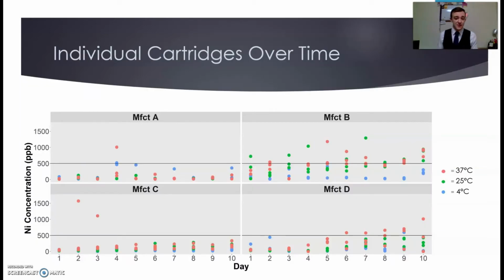This plot here shows individual cartridge nickel concentration for each of the 10 days for all 4 of the manufacturers we tested. And it really starts to show a lot of the relationships that we were able to extrapolate from this data. First off, this plot definitely shows the manufacturer variation, with manufacturers B and D experiencing many more cartridges above that black 500 parts per billion action limit line than manufacturers A and C.